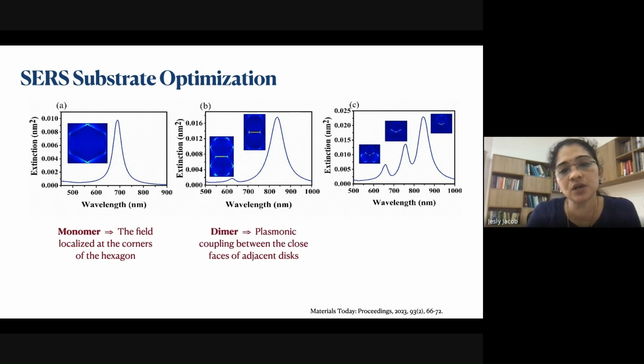Dimer structures show a little more local field enhancement because of the plasmonic coupling between the close faces of the adjacent discs, and also the corners will produce hotspots, and this will give a more improved extinction spectrum. And moving on to the trimer, it will have coupling from close corners in addition to this, and this will result in a more improved extinction spectrum.